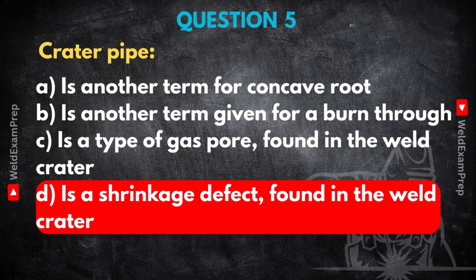Shrinkage defect. Okay, can you unpack that a bit? Sure. So when you finish a weld run, you leave behind a little pool of molten metal, the crater. As that metal cools and solidifies, it shrinks, it contracts. Right, things get smaller when they cool. Exactly. And if the welder doesn't properly fill that crater before stopping or pulls away too quickly, that shrinkage can cause the surface to pull inwards, forming a little hole or depression right at the end of the weld. That's your crater pipe. It's literally caused by the metal shrinking.